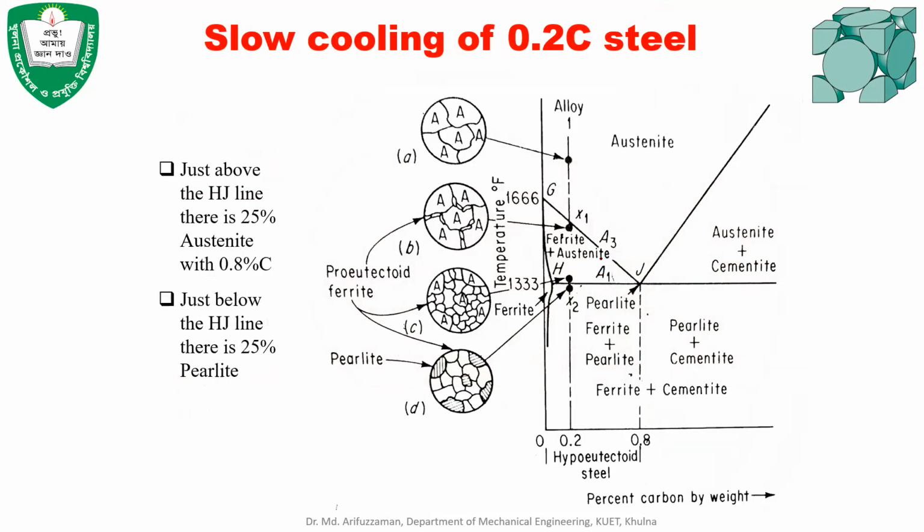That's the question. If you want to do the heat treatment, the main purpose is to retain some structure. To do that, you can do the slow cooling up to, let's say, this temperature. There will be a certain amount of ferrite produced, and the rest will be austenite. And then you suddenly apply fast cooling. Then the austenite structure will be retained. The final microstructure will contain ferrite and austenite instead of ferrite and perlite.